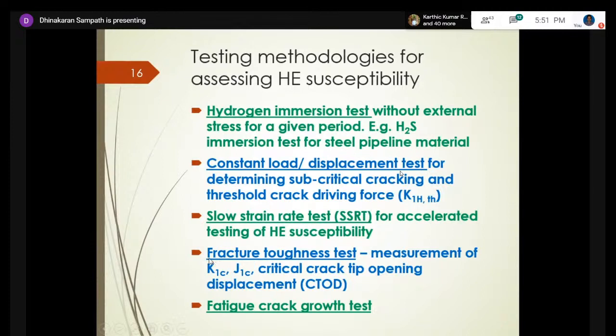So then the most concrete parameter to get is the fracture toughness test. This is also a very valuable test for life prediction. Fracture toughness, as I told, is the ability to evaluate the ability of the material to do unstable cracking in the presence of hydrogen. There are several fracture parameters like K1C, J1C, and then critical crack tip opening displacement. They are standardized and more or less considered a property of the material, but it's not. They are also subject to a lot of variability.